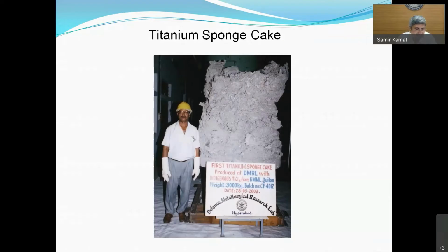So with DMRL technology, ISRO funding, and KMML as the nodal agency to set up this plant, the project started to build this plant in 2007 or 8. And by 2011, this plant was commissioned. There were a lot of teething problems initially, but by 2014-15, the commercial production from this plant started. But one of the issues is that, because of the limitation of funding, only a 500 ton per annum plant was established. Now, globally, most plants operate at 10,000 tons per annum.